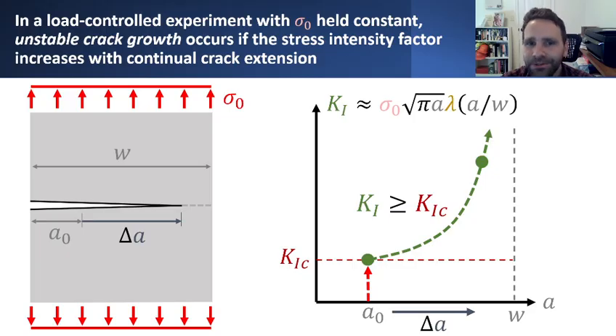For most load-controlled experiments, you will find that unstable crack growth will occur, and it precisely has to do with this. If you're holding sigma naught fixed, typically the dependence of K1 on the geometry and the extension of the crack will be an increasing one. So as the crack continues to grow at a fixed value of stress, the stress intensity factor will grow. Basically, what that means is that if you're trying to run a stable crack growth experiment by applying some load control, then you'll probably end up with the specimen just dramatically failing. And you'll never be able to achieve stable crack growth conditions in most cases.